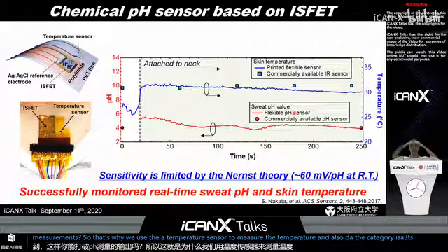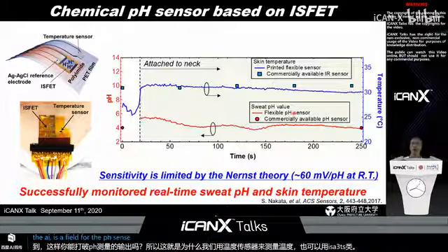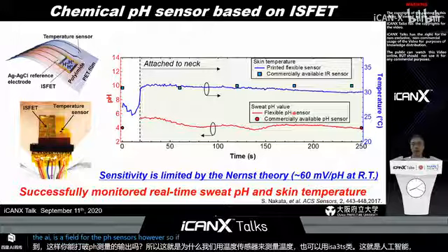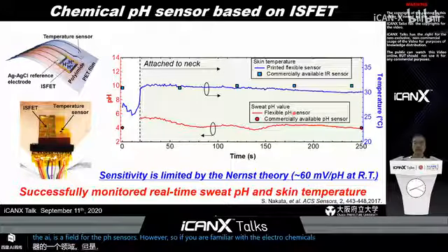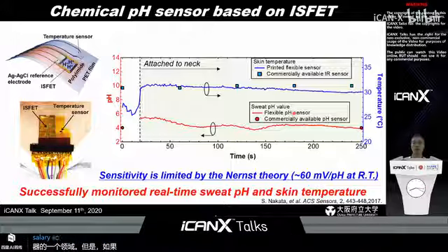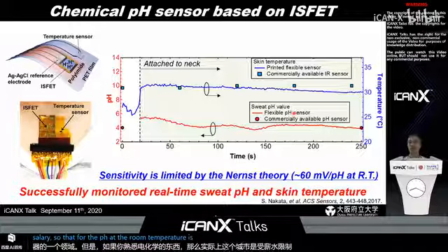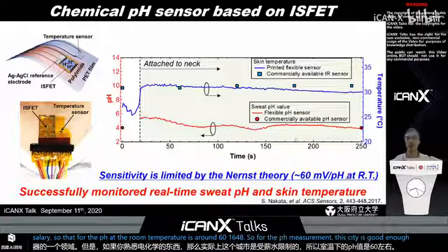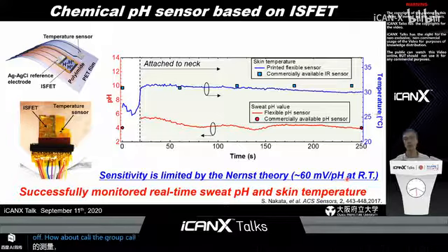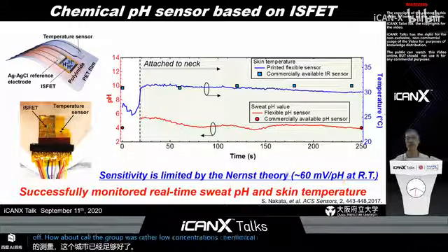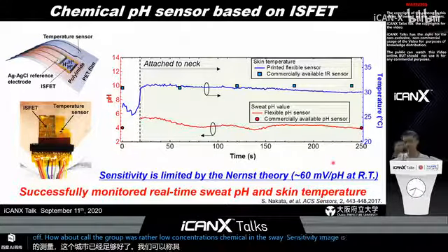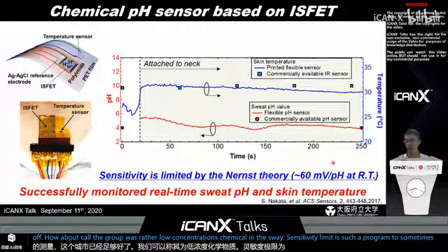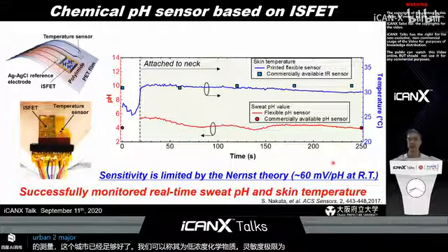So this is the ISFET for the pH sensors. However, if you are familiar with electrochemistry, the sensitivity is limited by Nernst theory, so that for pH at room temperature it is around 60 millivolts per pH. For the pH measurement, this sensitivity is high enough. However, for glucose or other low concentration chemicals in the sweat, this sensitivity limit is sometimes a problem for precise monitoring of the chemicals.